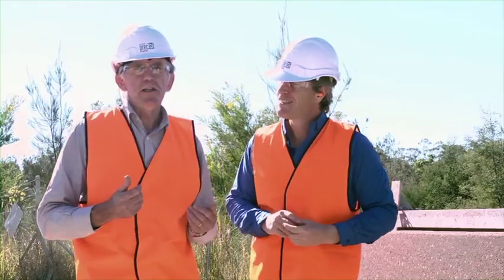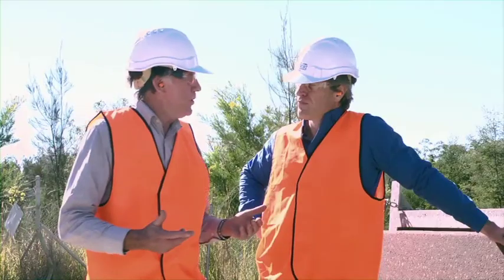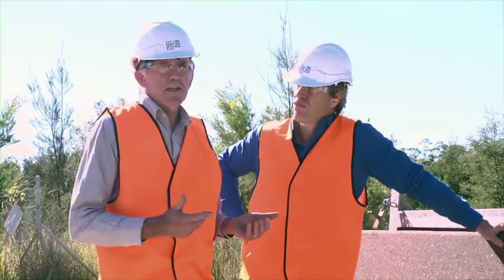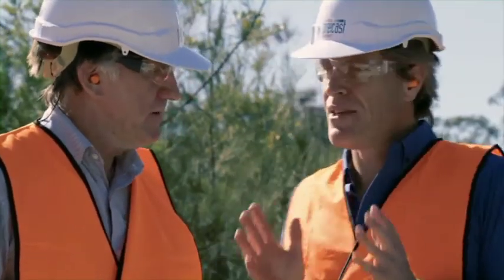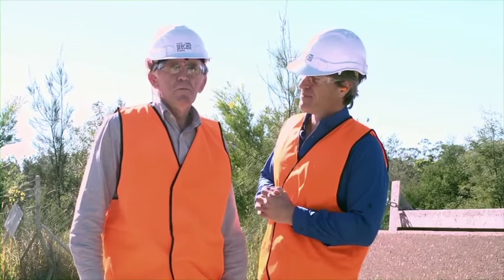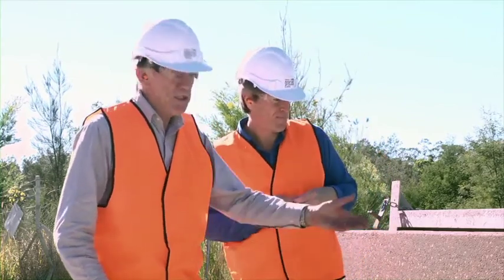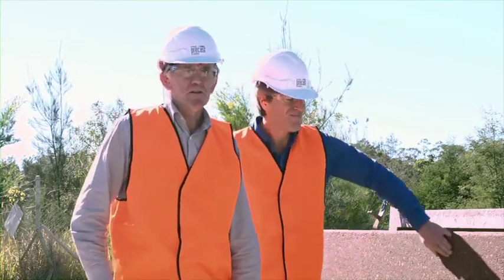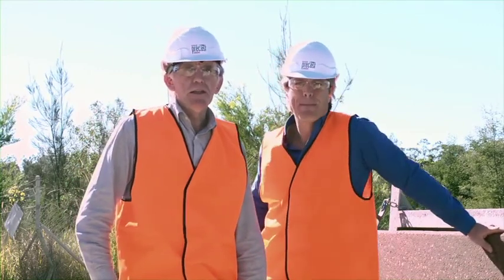The ability to undertake repairs on architectural concrete will often be severely limited due to the effect that the repairs will have on the finish. Thus, defects may mean that more product is rejected than would normally occur. Warren, are there any aspects where this is more likely the case? Well, particular finishes such as exposed aggregate are in themselves highly variable, and this is due to their process and the variability of the operation.